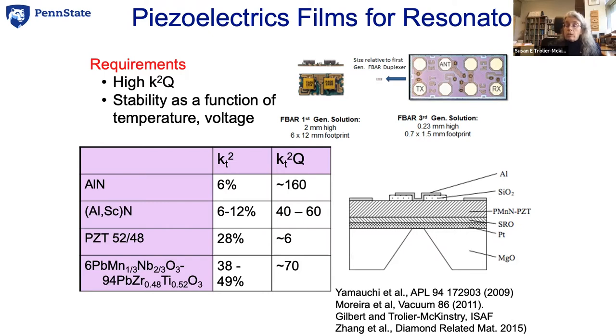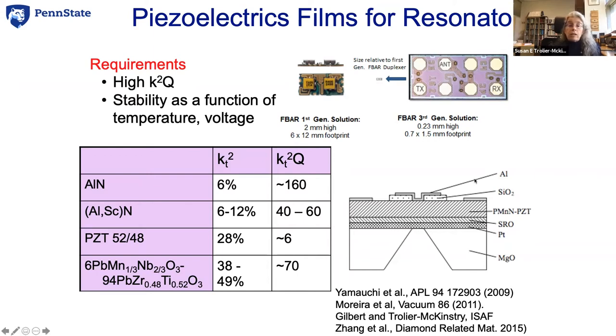Historically, this was done using dielectric resonators about half the size of a finger, made from high-density ceramic, that only worked on one frequency band. With modern cell phones needing many frequency bands for the 5G network, that became too heavy and too large. A number of years ago, we replaced those with tiny devices based on thin film piezoelectrics, where we oscillate the thin film in its thickness direction, and the coupling between electrical and mechanical energies changes the electrical impedance for the filtering function.